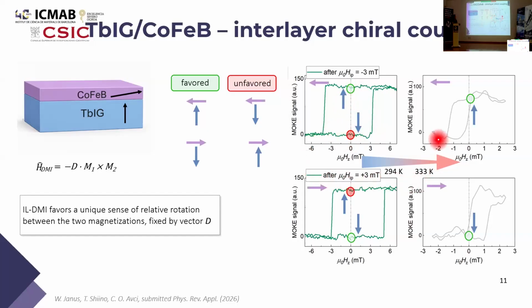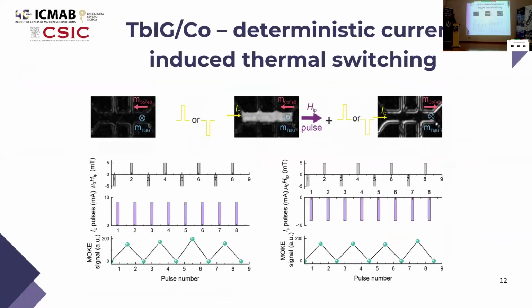However, if we increase the temperature, there is only one state possible, with the in-plane layer determining the direction of this out-of-plane layer. So simply, it means that if we set the unfavored state at low temperature and we increase the temperature, the magnetization of the out-of-plane layer will rotate in order to achieve this favored state. And this can also be done with electrical currents.